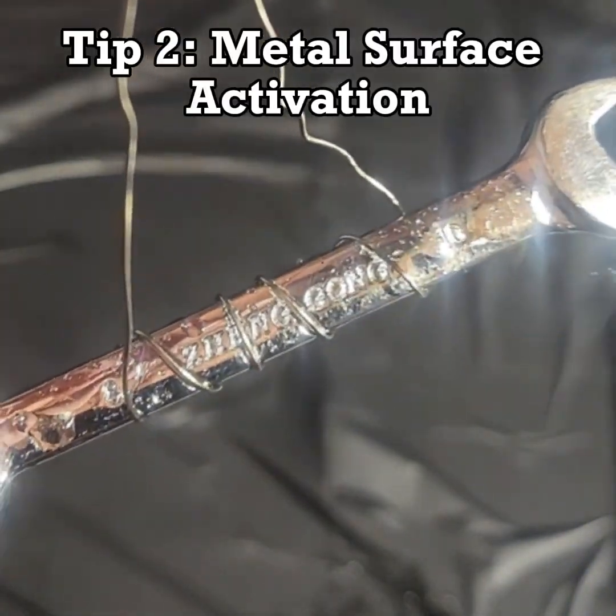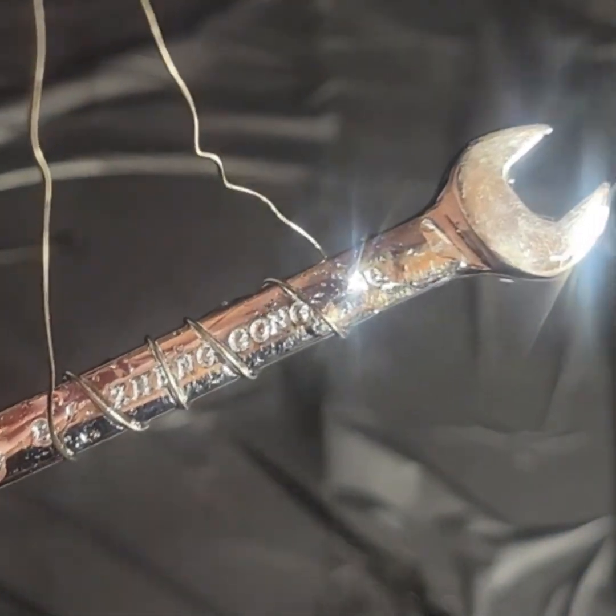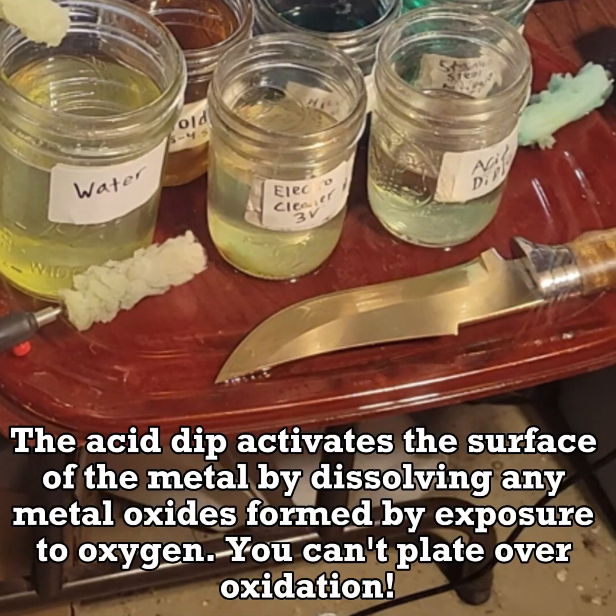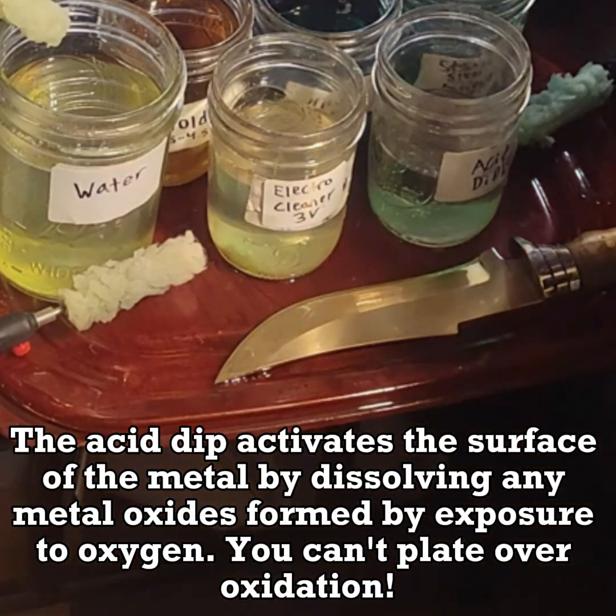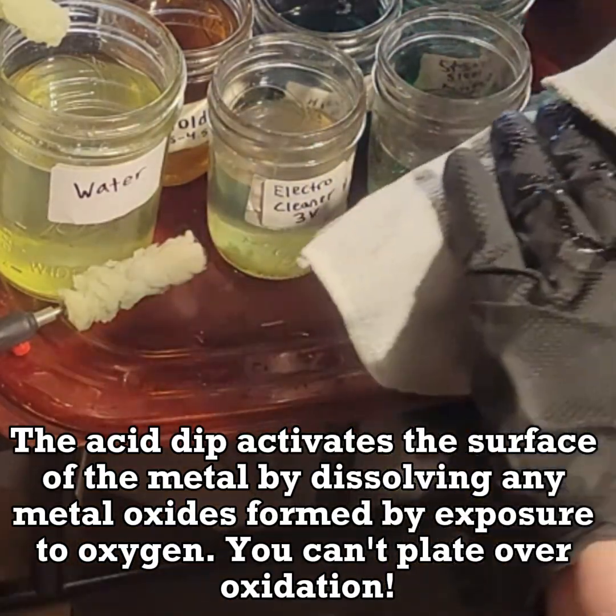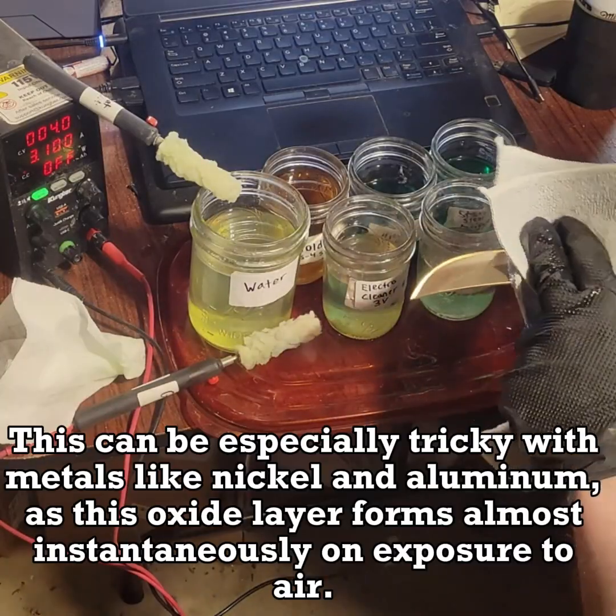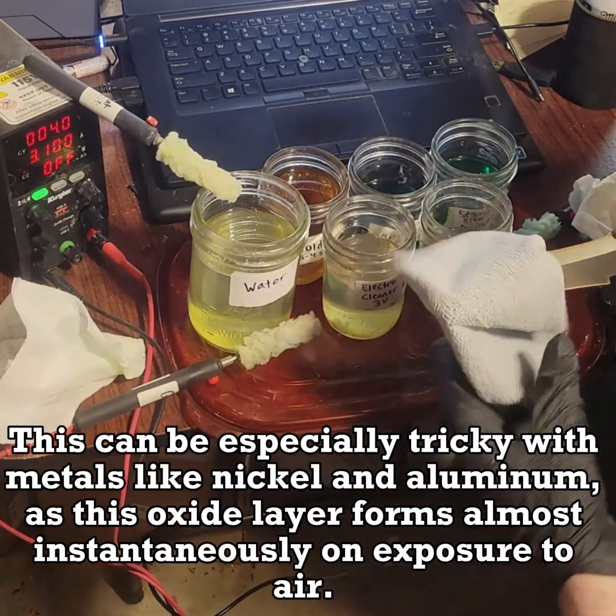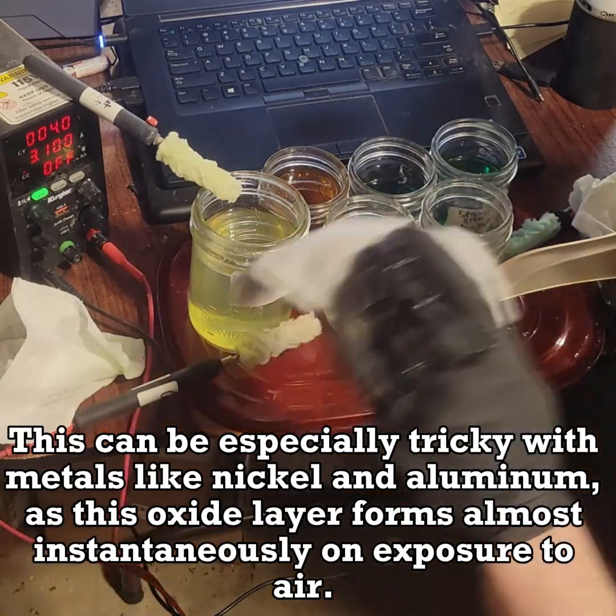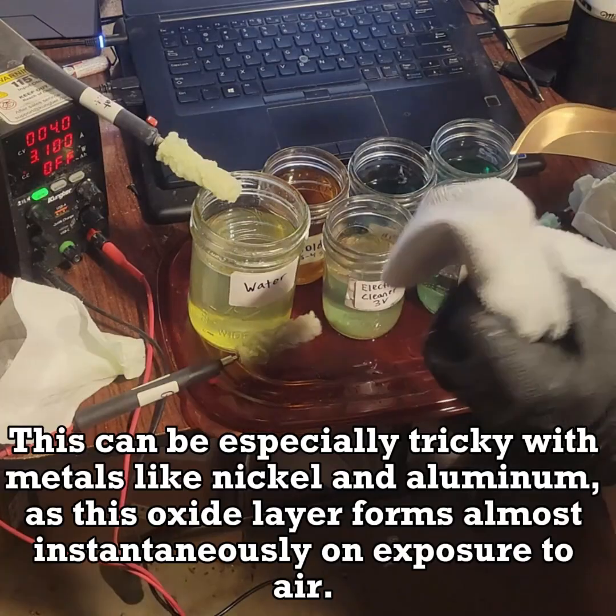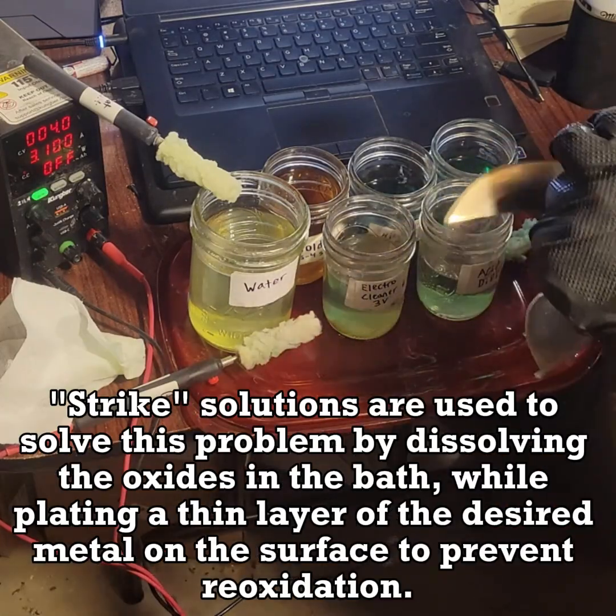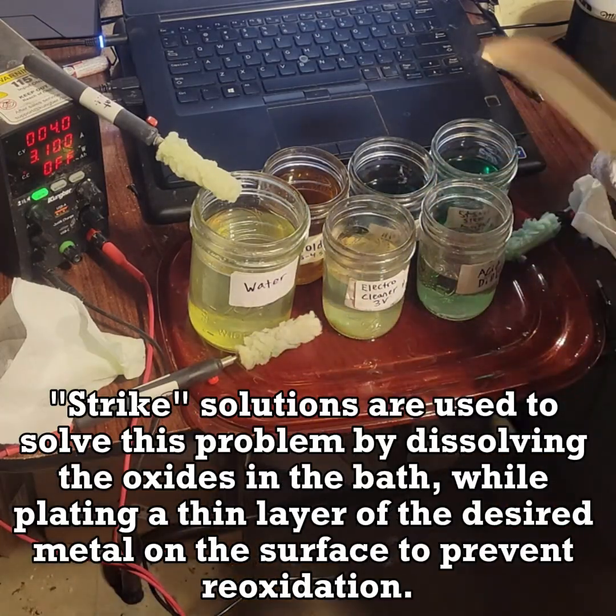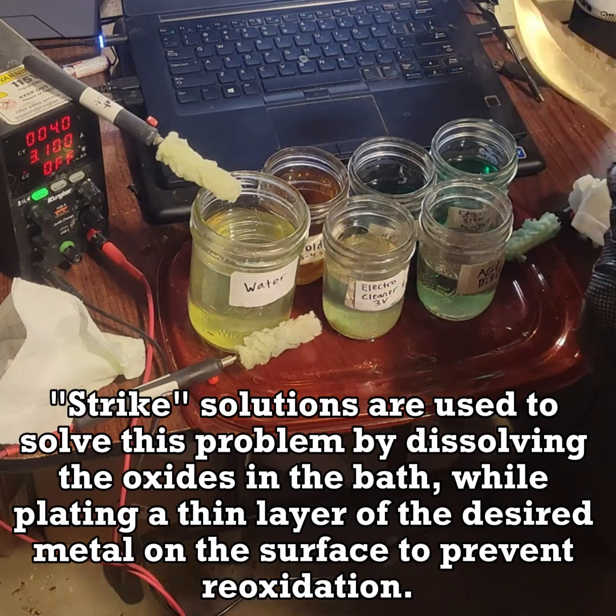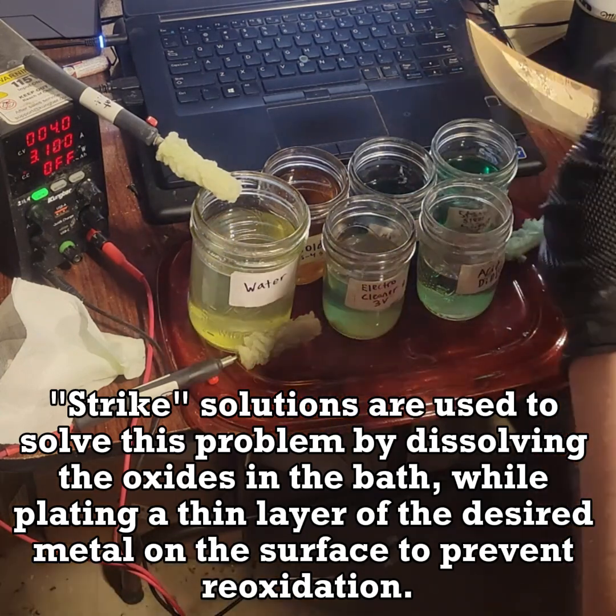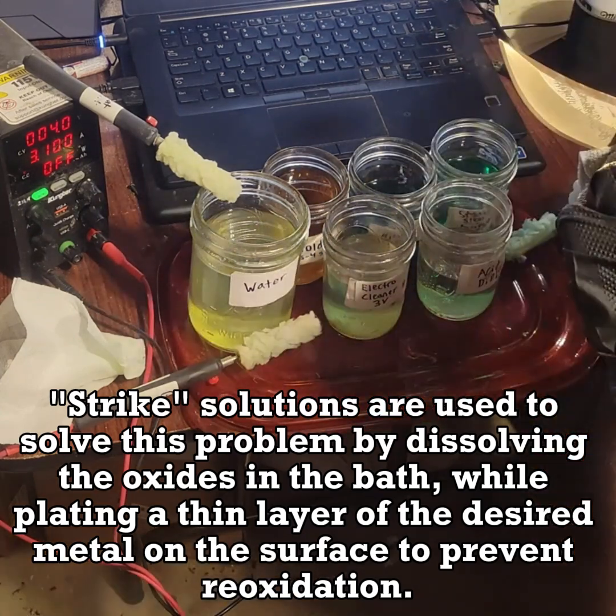Tip 2. Metal surface activation. The acid dip activates the surface of the metal by dissolving any metal oxides formed by exposure to oxygen. You can't plate over oxidation. This can be especially tricky with metals like nickel and aluminum, as this oxide layer forms almost instantaneously on exposure to air. Strike solutions are used to solve this problem by dissolving the oxides in the bath, while plating a thin layer of the desired metal on the surface to prevent reoxidation.